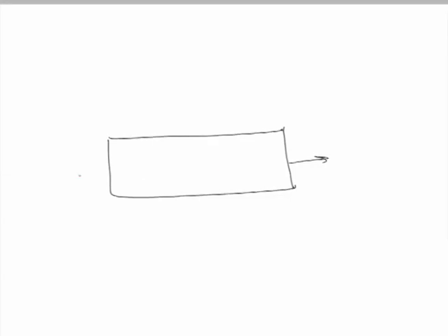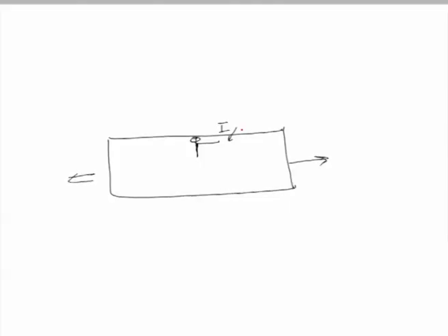To understand this, we can look at another schematic diagram. Here we can see that under fatigue load conditions, in this component, due to the load fluctuation in the initial stage, a crack has nucleated and then it will be growing gradually. Stage 1 is very limited, say 10 to 15 or 20% of the fatigue life cycles, and then in stage 2 the crack will be growing very stable and slowly. With the growth of this crack there will be a reduction in the load-resisting cross-sectional area.